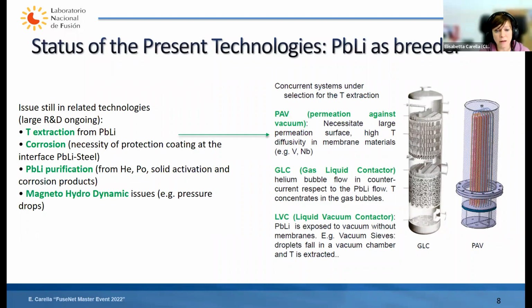Then we also have to purify the lead lithium from all the solid activation and corrosion products that will be produced inside the breeder tubes. And related to the movement of this lead lithium, which is a metal, we have a magnetohydrodynamic problem with the coils, because this is a metal, so its movement can produce a recirculation of current and additional magnetohydrodynamic effects on this liquid metal moving inside the water-cooled breeder blanket, apart from some important pressure drops.